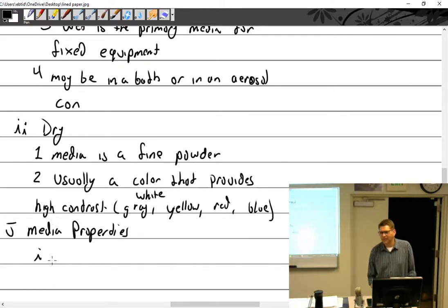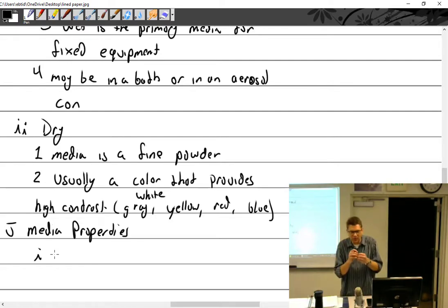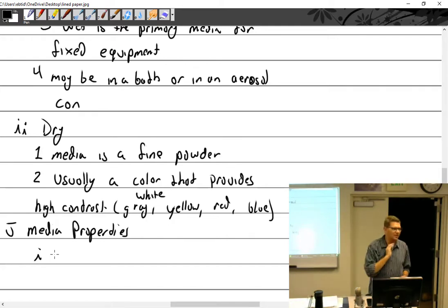All right, so we were tasked with developing these fine little particles that go in either the Magnaglo carrier or the fine dry powder. What magnetic properties would we use to describe what we want to use? So would we want something that has a high or low retentivity? The little particles are going to show us where the crack is. Low retentivity so that you can reuse them. All right, so low retentivity.